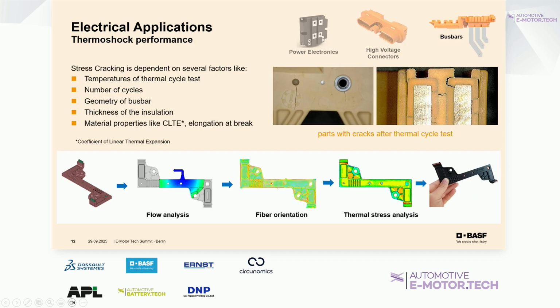The third example I have here for you is regarding bus bars. They play an important role if we talk about the e-engine. Here we have also another test additionally coming, the so-called thermocycling test. So you see here, typically you have a kind of expansion behavior from your metal and your plastic. And if you increase and decrease the temperature, at the end of the day, you still want to have a working application. And you want to avoid something like that here, like having these cracks here on the surfaces, which might cause a failure at the application.